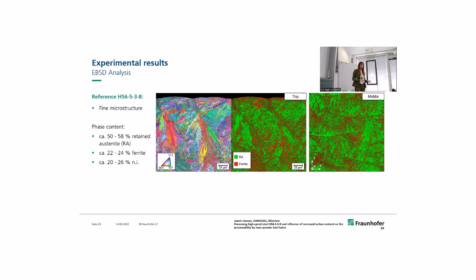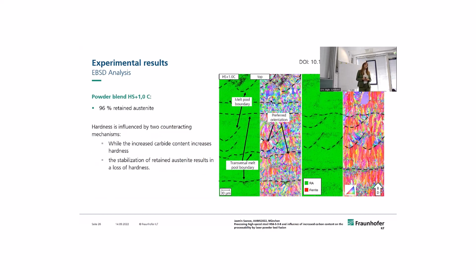A lot of ferrite or martensite. We didn't do a further investigation, so it's just BCC or FCC. But also, and this is something very crucial, a lot of not identified areas. So that's really a lot. So we really have to be careful with interpreting the results of the phase content of retained austenite and martensite. But this result is very, very clear.